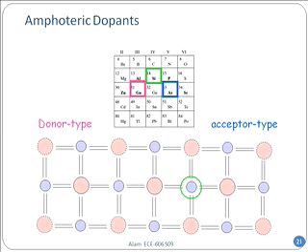Now this moving from one to another, many times you have the LEDs. There are these white LEDs that are being used in many places, street signs and others. One of the problems, and many professors spend their lifetime on this, is making sure that it preferentially goes to one place versus the other. There are many materials where it only wants to go to, let's say, the gallium side, and doesn't want to go to the other side. And sometimes it will go equally on both sides, and eventually you don't have anything constructive because some gave an extra electron, others took it out. And at the end, you're back to your intrinsic semiconductor.